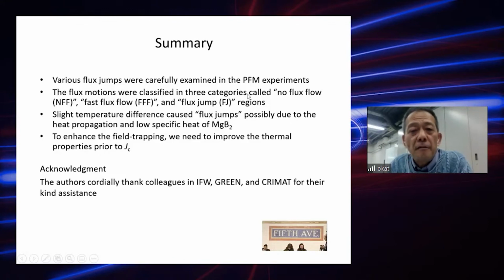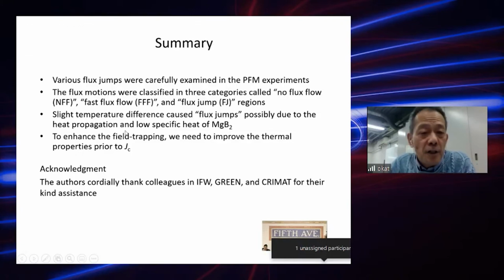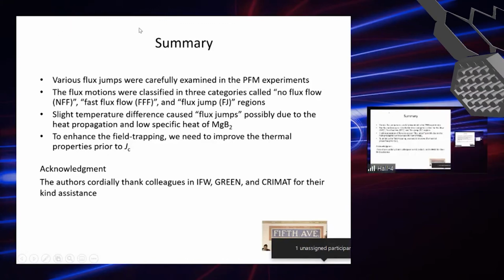So then we must summarize my talk. The various flux jumps were carefully examined in a PFM experiment. The flux motions were classified in 3 categories of the NFF and FFF and flux jump regions. Very slight temperature differences caused flux jump, possibly due to the heat propagation or the low specific heat of the material. To enhance the flux trapping, we need to improve the thermal properties prior to JC values. Thank you so much for your attention.